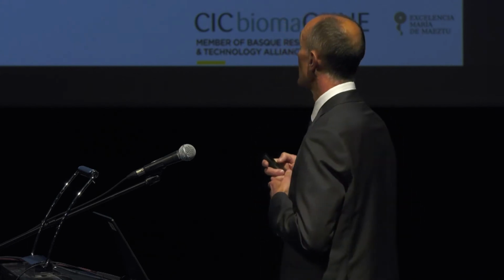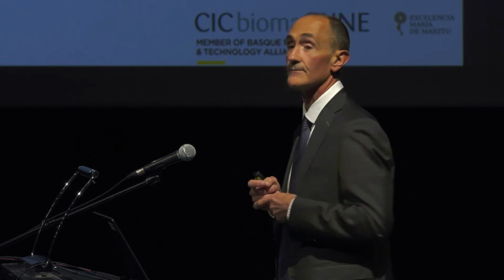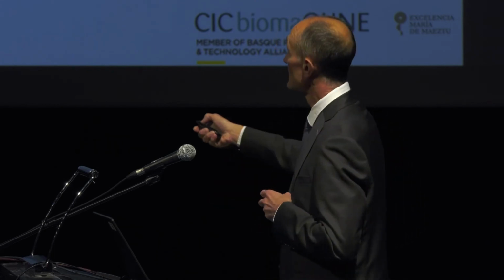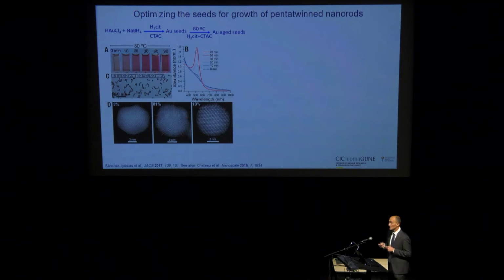Recently, inspired by the work of Stéphane Parola in Lyon, Marek Ziółek together with Ana Sánchez Iglesias started exploring the ripening of the pentatwin seeds. Again reducing with sodium borohydride, now in the presence of a mixture of citric acid and CTAC, they were obtaining what we would call very low quality seeds. But then by incubating at 80 degrees for a couple of hours, even 1.5 hours, they were seeing a gradual increase in the particle size, but also a large increase in the proportion of particles that have the 5 twins. And these are again images coming from our colleagues in Antwerp.